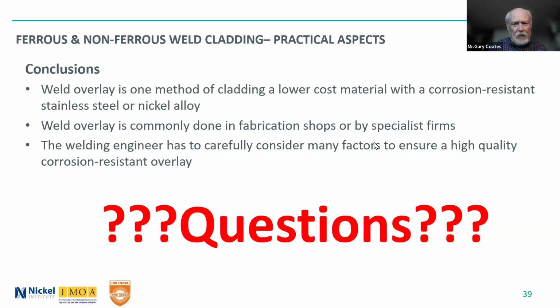Next question was why annealing is not required in explosion cladded. Well, the reason is that there is no heat, or I should say a very, very minimal amount of heat involved. With roll cladding, the other way of cladding, you're actually exposing it to very, very high temperatures for time, so you must do an annealing afterwards. But explosion clad, you don't need to do an annealing, but you really need to do a stress relief because you are putting a lot of stresses into that material.